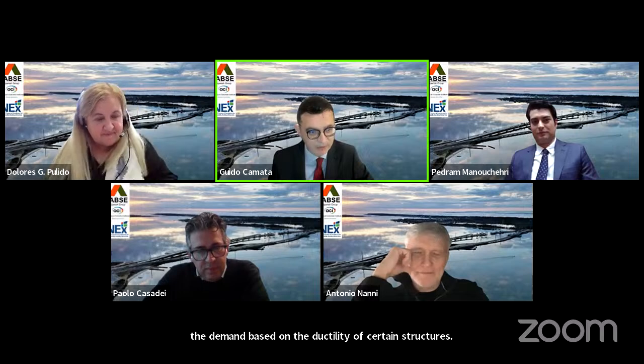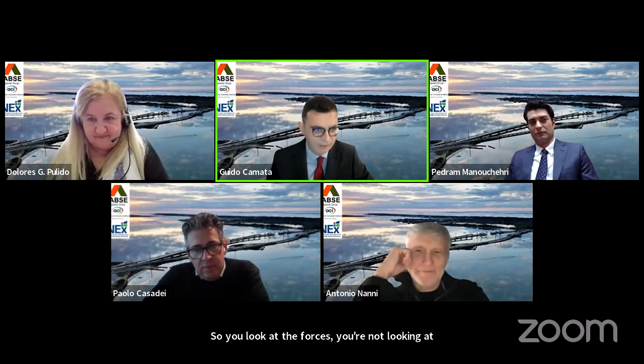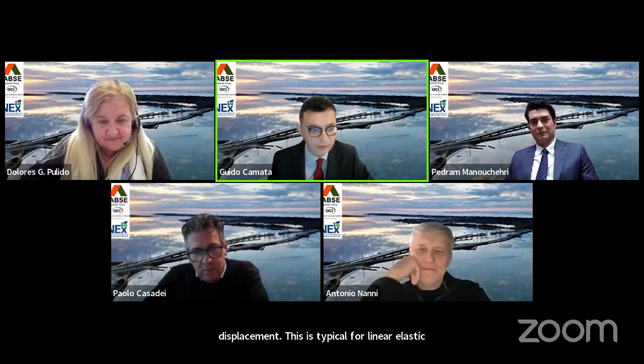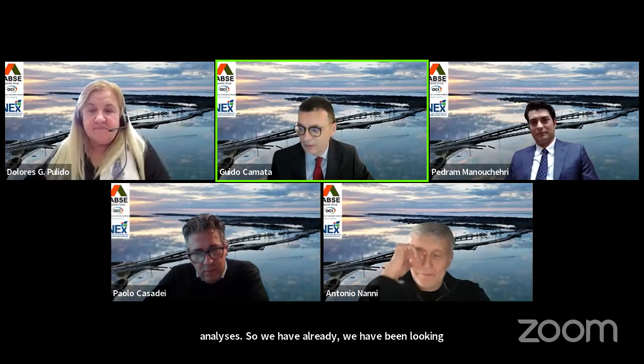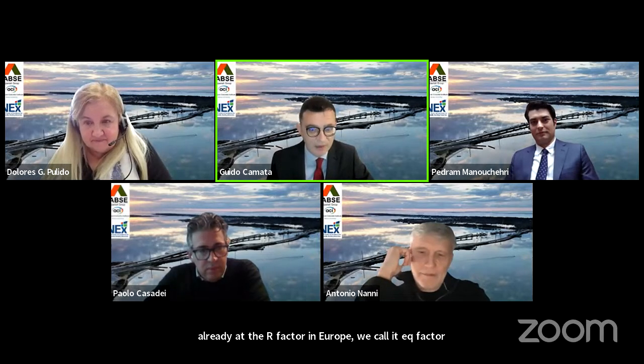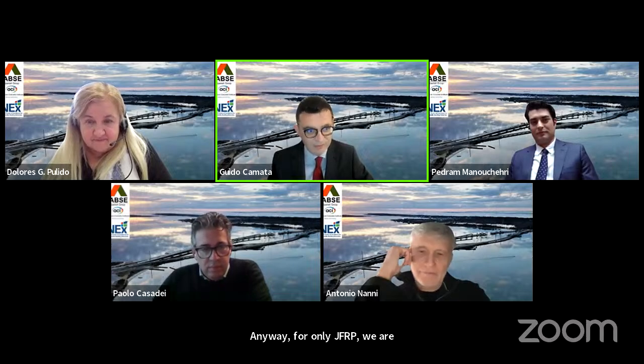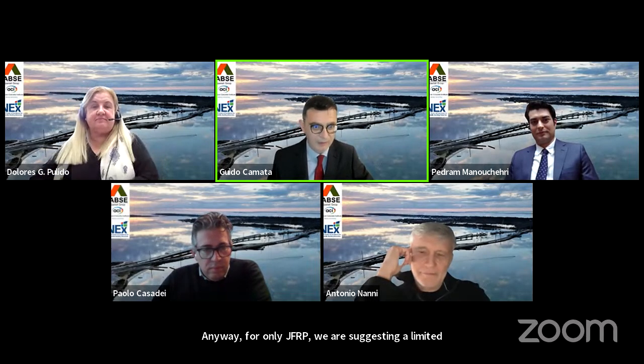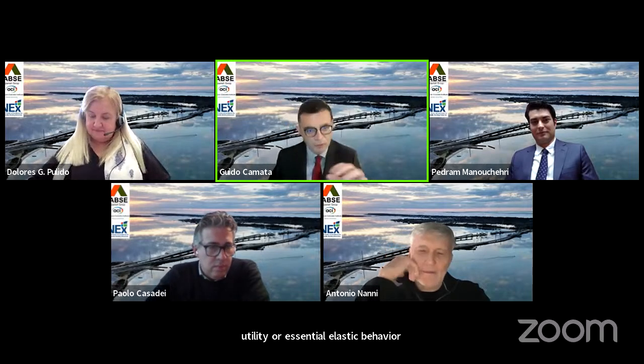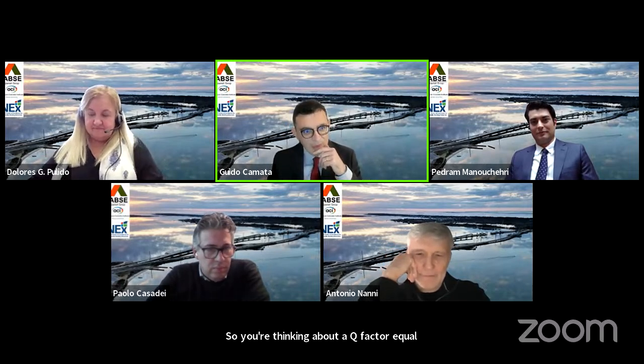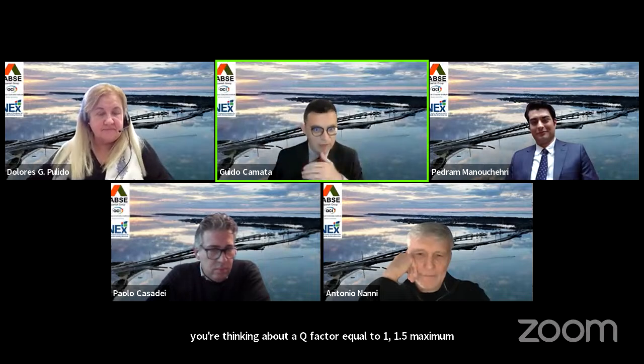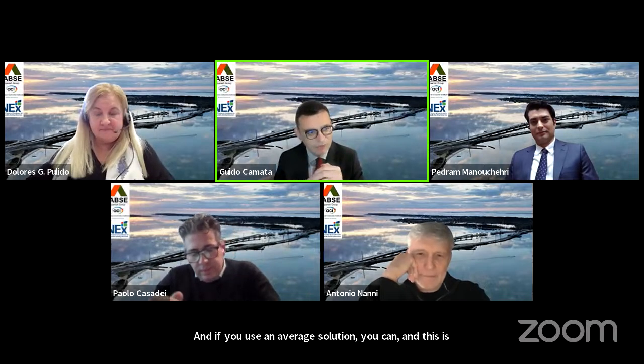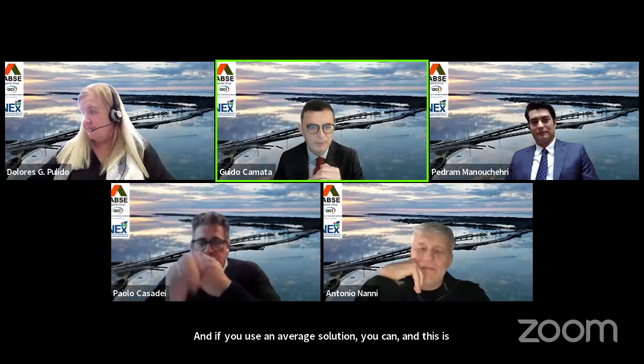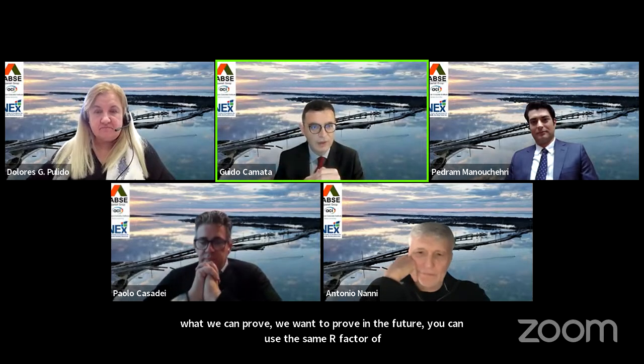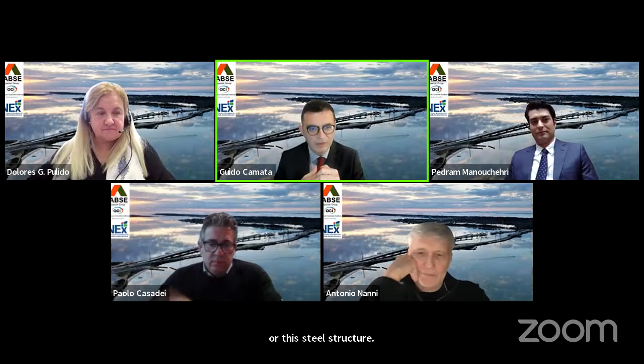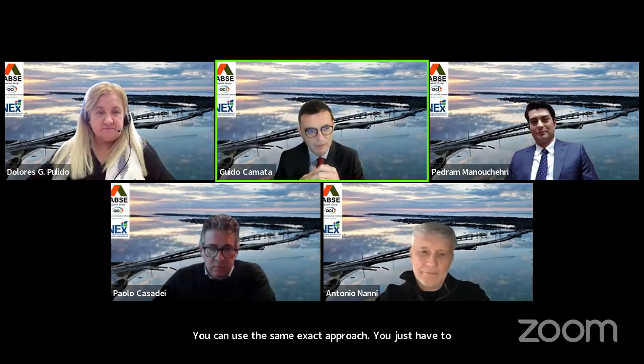So we have been looking already at the R factor in Europe. We call it Q factor. Anyway, for only GFRP, we are suggesting a limited ductility or essentially elastic behavior. So you are thinking about the Q factor, R factor equal to 1.5 maximum. And if you use a hybrid solution, and this is what we want to prove in the future, you can use the same R factor of the steel structure. So you can use the same exact approach. You just have to define correctly the R factors.